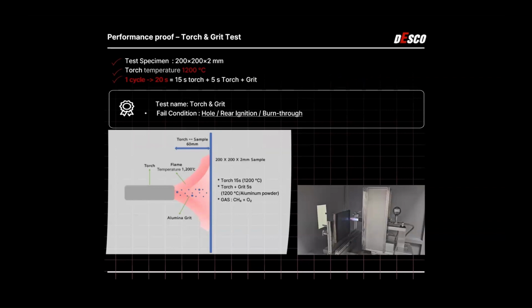Torch and grit test is one of the most demanding thermal tests in industry, and a standard required by global leaders like HKMC and UL. Here's how it works. We take a 2 millimeter thick sample of our material, 60 millimeters from the torch, and we blast it with a torch flame heated to 1,200 degrees Celsius. The test runs a 20-second cycle. For the first 15 seconds it's only torch, but for the final 5 seconds, we add abrasive aluminum grits into the flame to simulate the high energy particle spray from an exploding cell.